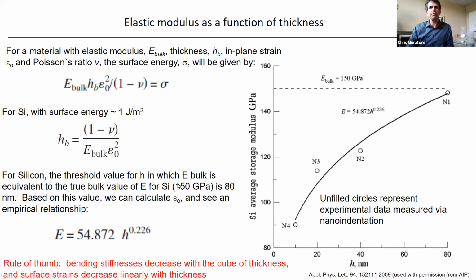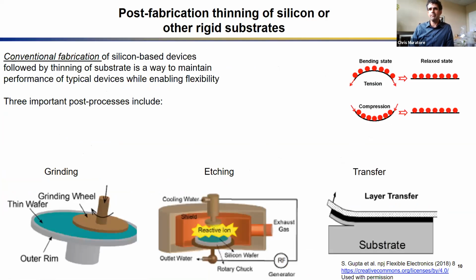So I can take this elastic modulus for bulk silicon and plug it in, and I can see what the thickness is below which I start to deviate from the bulk elastic modulus. And so it's about 80 nanometers, right? So around here, I start to deviate substantially from the elastic modulus. So I can make a calculation that helps me to know what kind of thickness range do I need before this material really changes its properties and starts to become a lot more flexible.